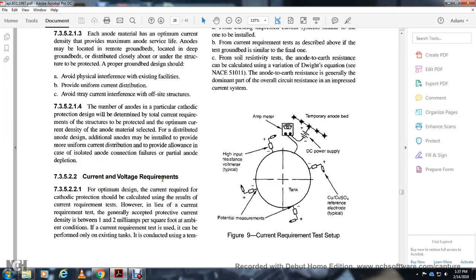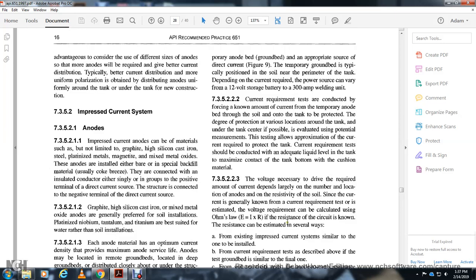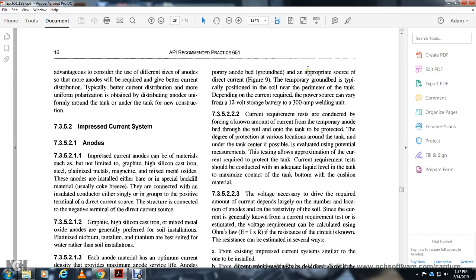7.3.5.2.2 The current and voltage requirements. The optimum design of the current required by the cathodic protection should be calculated from the results of the current requirement tests for the tank. A generally accepted protective current density is between 1 and 2 milliamps per square foot of bare surface. Current requirement tests are performed on existing tanks, using a temporary anode bed or ground bed in the appropriate soil with a direct current source. The temporary ground bed is typically positioned in the soil at the perimeter of the tank. The power source for the current required can range between a 12 volt storage battery and a 300 amp welding unit.